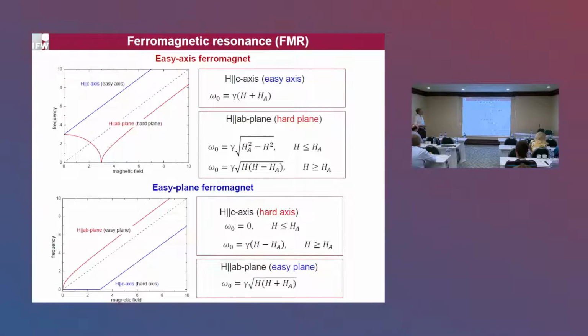Now, in the case of ferromagnetic resonance, which will be the subject of my presentation today, in principle, in a one-sublattice ferromagnet, one can excite two modes by ESR. They are degenerate at zero magnetic field, and they have finite energy in the case of easy axis anisotropy. That means the magnetization, or the spins, prefer to stay out of the plane. In this case, if one applies a field normal to the plane, one mode will develop linearly with magnetic field. The other mode will first soften, and then it will also develop linearly in a magnetic field. This is distinct from the paramagnetic resonance, whose branch is shown here.